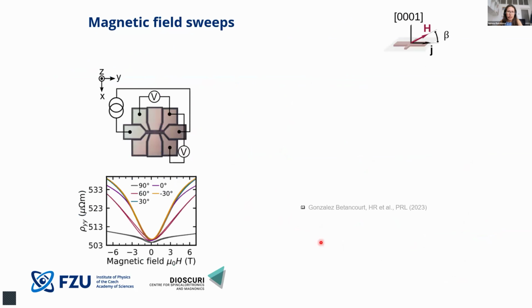And this is indeed what we did some time ago: on manganese telluride films we patterned very simple, very standard Hall bars, and in this geometry we then apply a magnetic field. Here, I just show the geometry. This is the c-axis, the out of plane. Here it's the AB plane, and the magnetic field in that case I show along some arbitrary angle with respect to the sample plane.